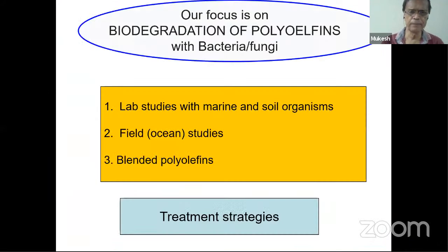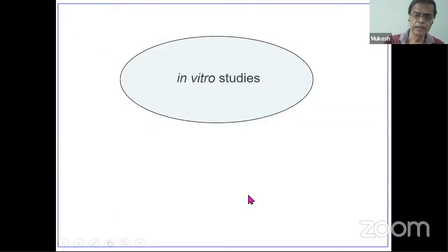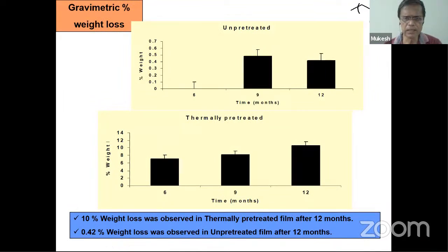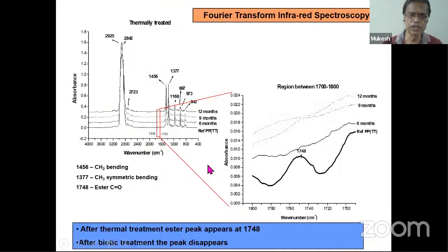So let me briefly talk about some of the studies we have done in the lab, in the field, and so on. As you can see, when we heat the polymer and then try to degrade it, it degrades faster over a period of time. In 12 months, we see good weight loss, almost 10% weight loss in the polymer when compared to the untreated polymer, where the weight loss is very, very small. So heat treatment helps in the degradation of the material.